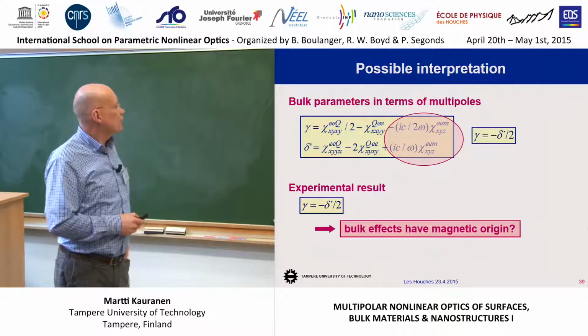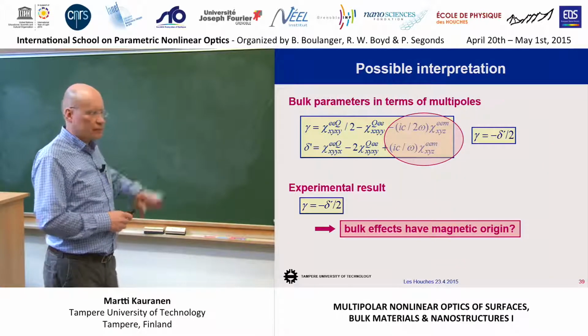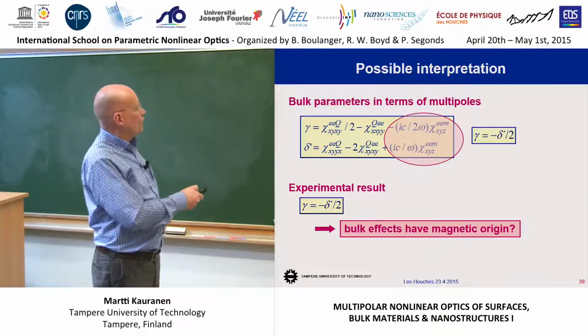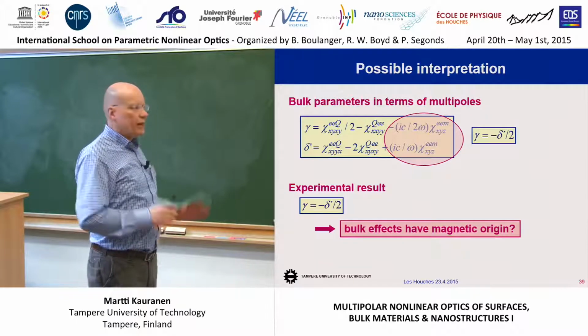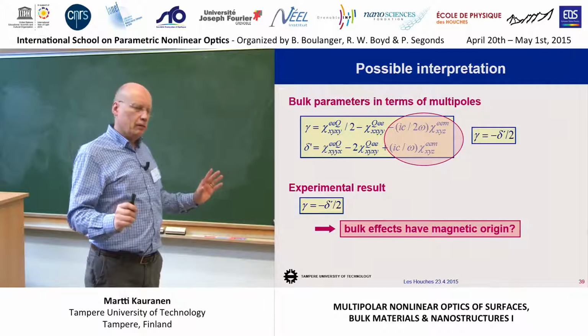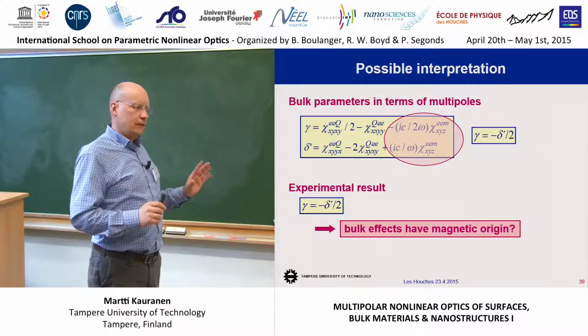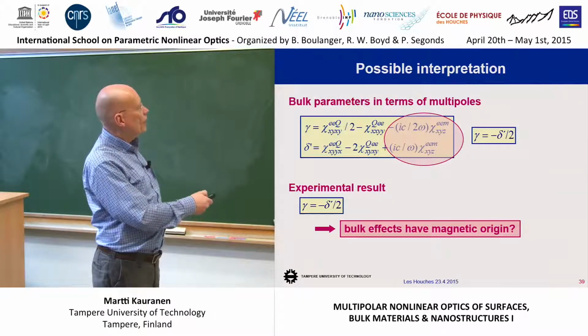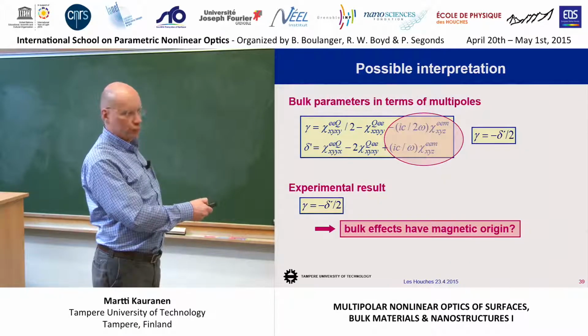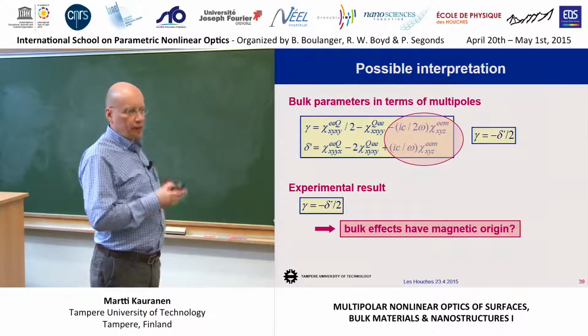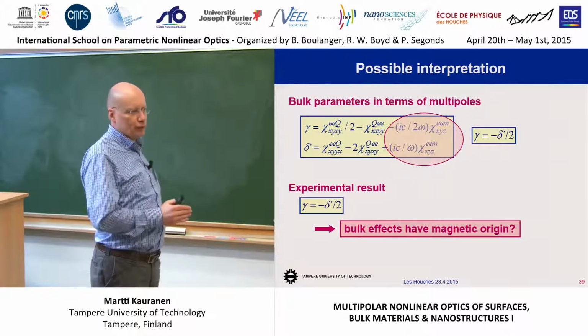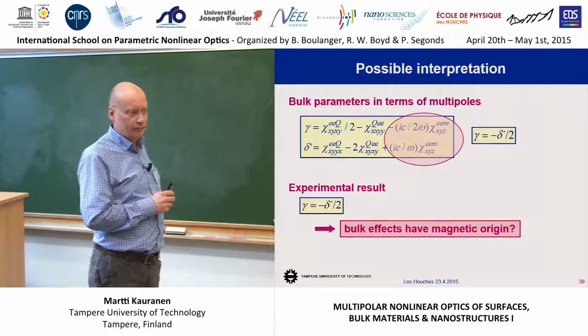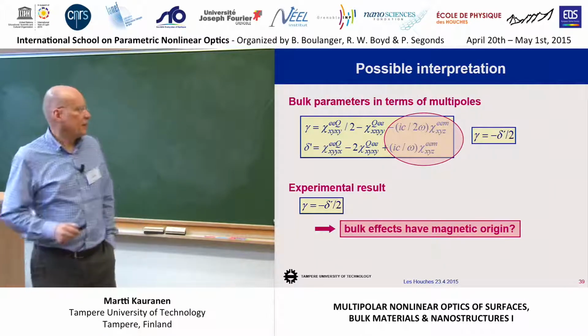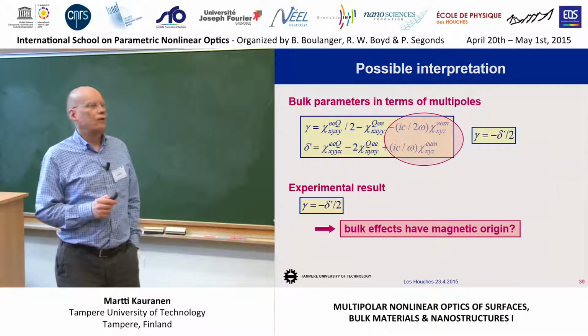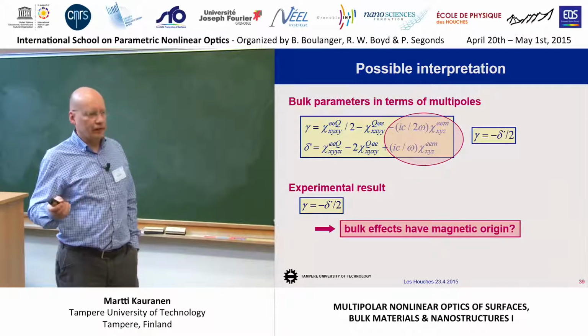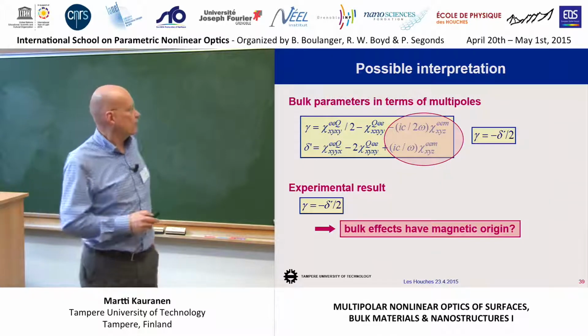And then let's go to these theoretical expressions for the gamma and delta parameters. Beta is not important. When you look at the quadrupole part and the magnetic part, if you assume that the bulk response is only due to the magnetic interactions, you find that gamma should be minus delta over 2. And this is what we measured in the experiment. So it's very tempting to say that the bulk contribution has a magnetic origin. Why? We don't know. But incidentally, at the same time when we worked on this, there were other papers where people suggested that various glasses have stronger than expected magnetic responses. But these are really vague connections.